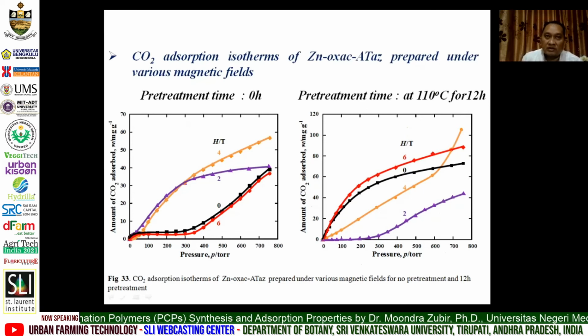the interaction between CO2 and the amine group induces a significant amount of carbon dioxide captured in the frameworks. This is the left side for 0 hours pre-treatment time, no pre-treatment, and this is pre-treatment at 110 degrees Celsius for 12 hours. The 0 Tesla and 6 Tesla, which have the same XRD pattern, cannot adsorb carbon dioxide at low pressure below 400 torr. But after 400 torr, there is a significant increase in the CO2 adsorption amount. Especially for 2 Tesla and 4 Tesla,